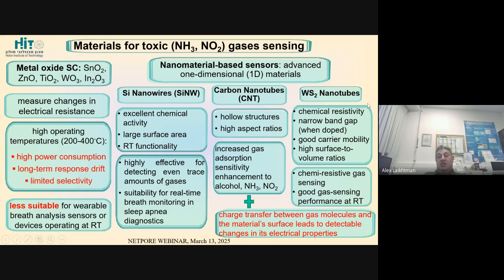WS2 nanotubes can provide added value because of their chemical resistivity. They are very inert, so they are not destroyed in the atmosphere or even at relatively high temperatures. If doped, they have quite a narrow band gap, but even if not doped, their band gap is okay. Good carrier mobility, high surface to volume ratio, so they can be used as chemiresistive gas sensors, not supposed to be destroyed by NH3 or NO2. And they have good gas sensing performance at room temperature, because of charge transfer between gas molecules and the material surface.